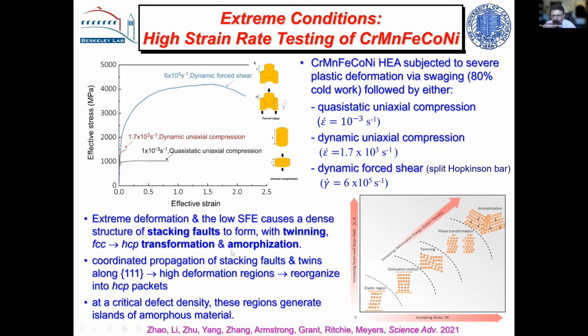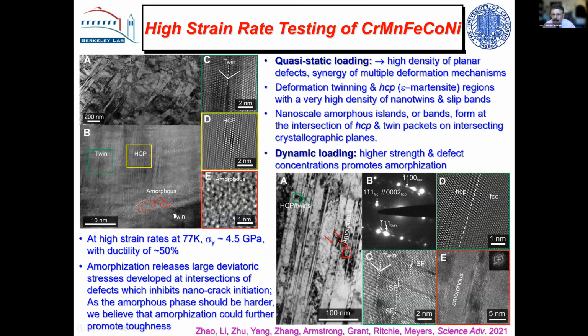split Hopkinson bar. But we start to see all those mechanisms that I talked about, but in much greater magnitude. So we see a lot of twins, very, very fine twins forming, much finer than we saw at room temperature. You can see them here as well. And we also see regions of the hexagonal phase, but very little and in very, very narrow bands. And we see amorphous material. We actually form amorphous material at these very high strain rates. So we're getting ductilities of 50% at these very high strain rates, but we're getting ultimate strengths which are approaching, well, over 4 gigapascals.